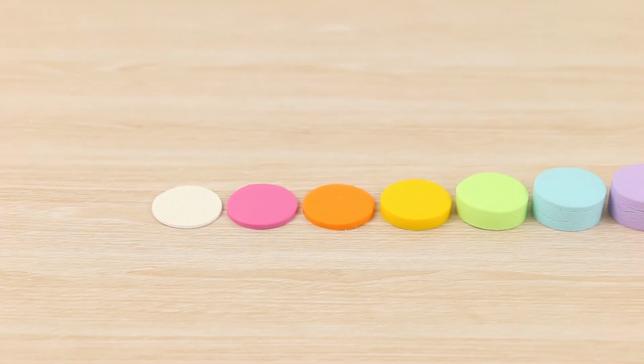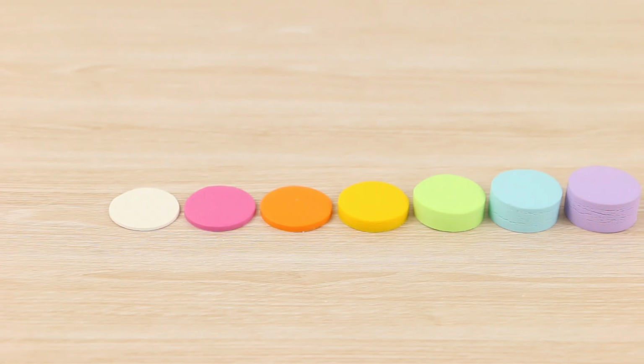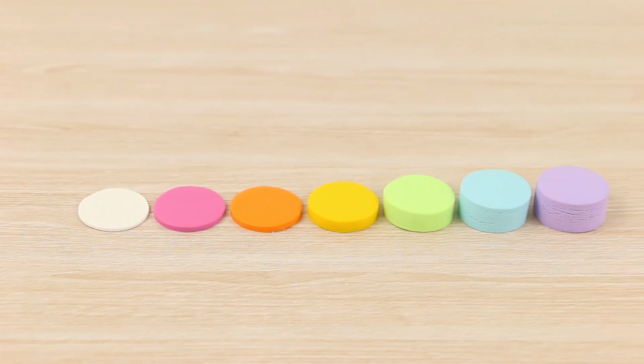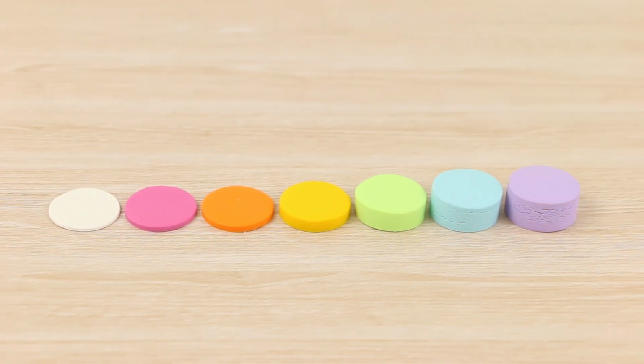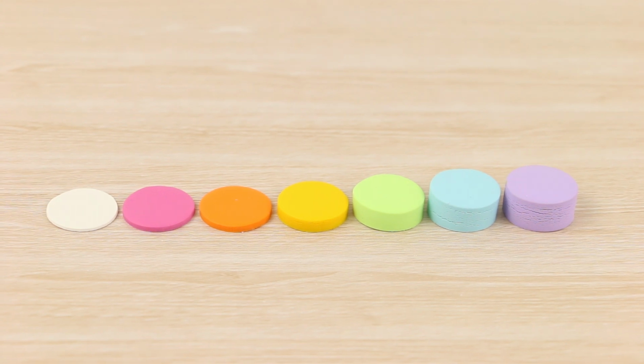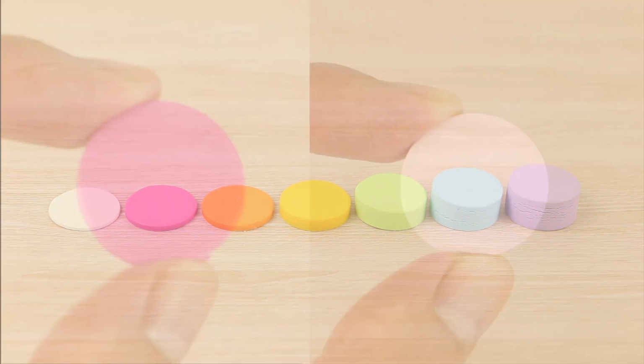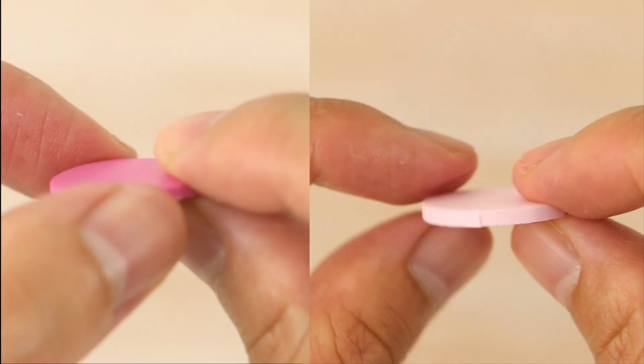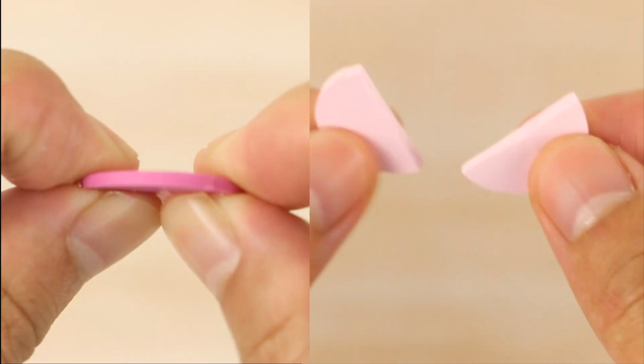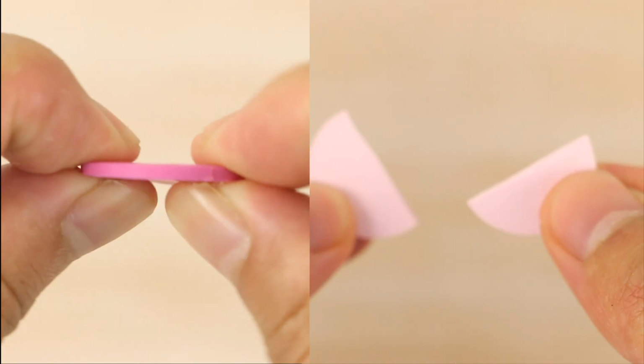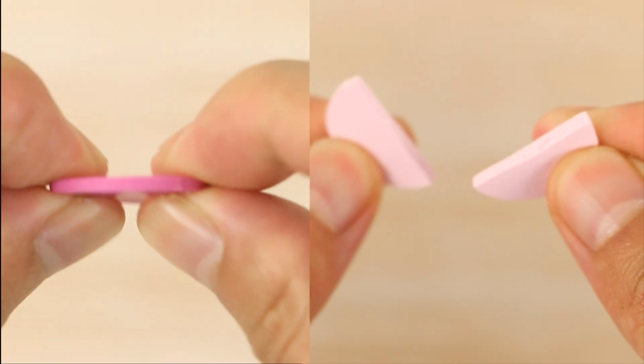Then finally bake some test clay in various thicknesses for different amounts of time, making sure that your baking surface is as close to the center of your oven as possible for even baking. And then once they've cooled down completely, test the strength by flexing the clay and not bending it. Strongly baked polymer clay is flexible since it's made of vinyl plastic, and weakly baked clay will snap in two.